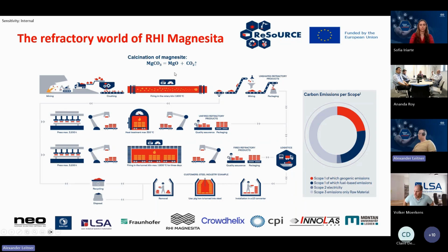That's just highlighting again where we have our high carbon footprint, right? One of the main raw materials used, I mentioned, is magnesium oxide, and what's mined is magnesium carbonate. So if you would like to produce MgO, you need to heat that at a very high temperature, and you will release CO2, which comes out of this so-called raw material magnesite. Very hard to prevent. However, if you go through the full circle, your product is used by the customer and then recycled. Of course, we are then not entering the primary raw material production cycle anymore, so we really get rid of the CO2 emissions during calcination, and that's exactly the reason why we have this very high benefit in terms of CO2 savings when recycling is used.